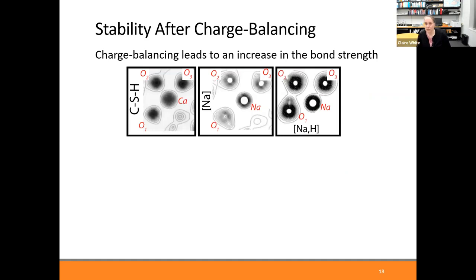So we can look at things such as bond strength, the impact of having the hydrogen in the system on the bond strength. And so if you look here, this is the baseline CSH. What we're looking at is electron density contour plots between different atoms. And specifically here, we're looking at between an interlayer calcium and surrounding oxygen atoms. If that calcium is replaced by sodium, you see that the electron density contour plots, well, the contours, there's less of them. And also they're not as black, which is giving you an indication that there's weaker bonding happening between these atoms.